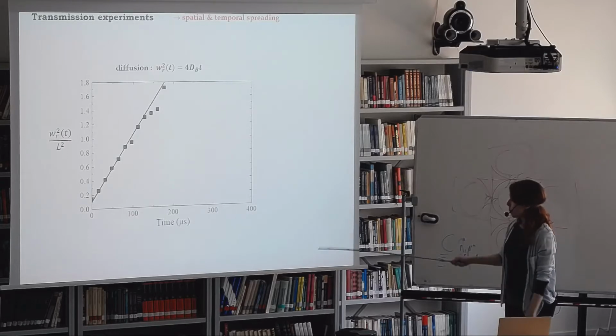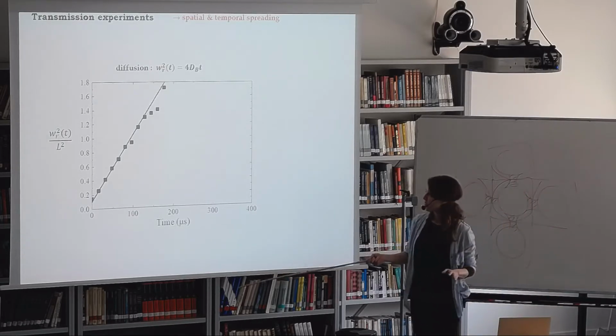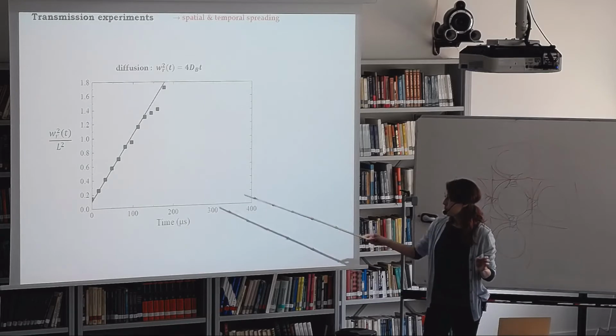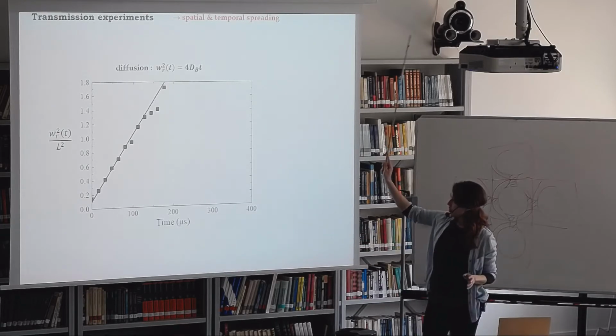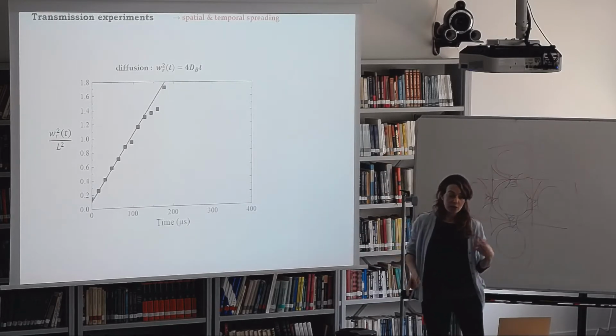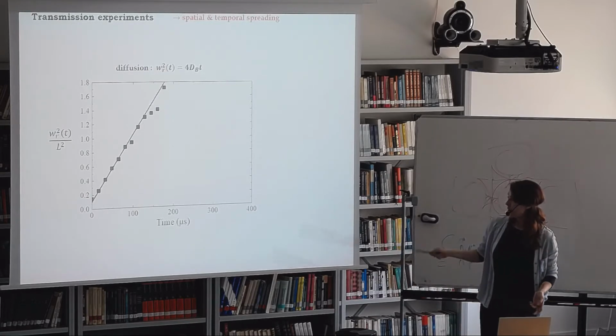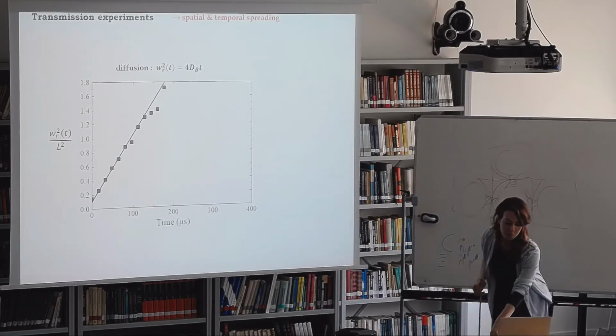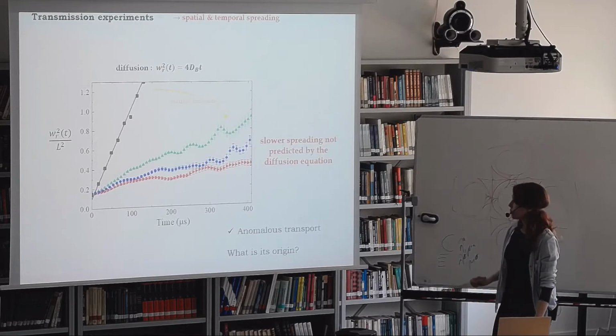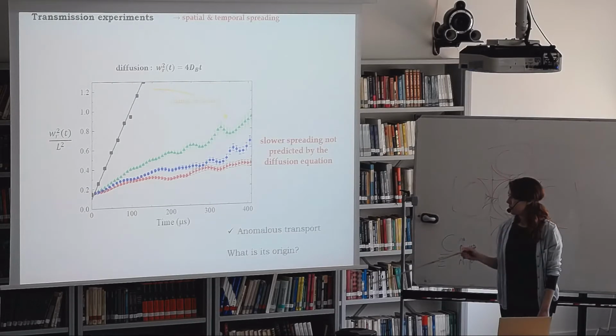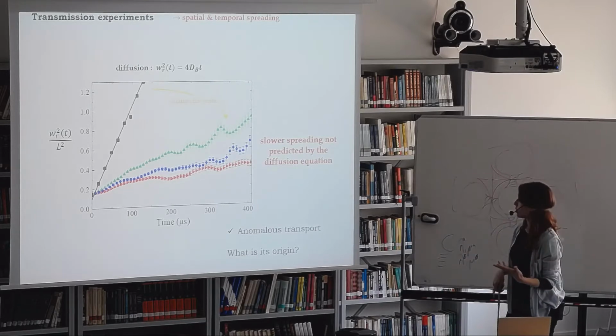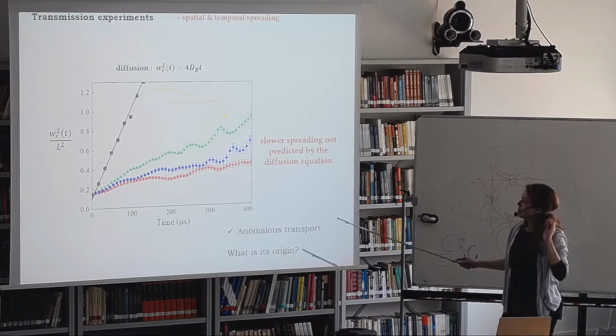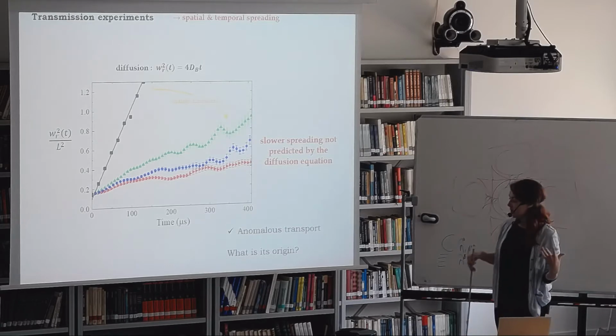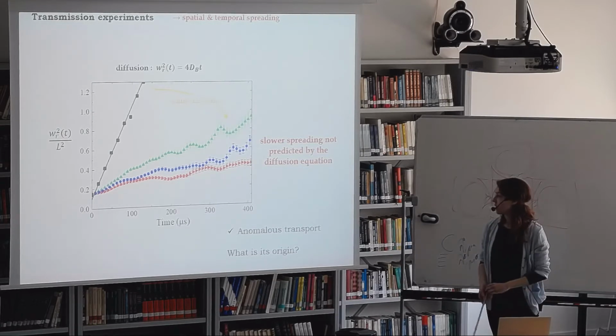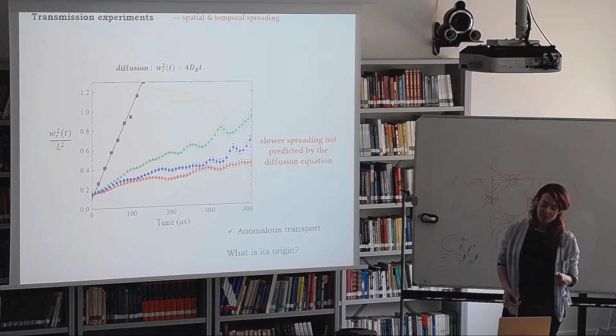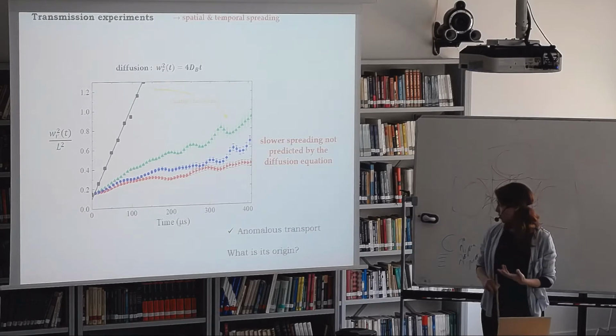Here we see the width squared, normalized by the sample thickness, as a function of time. As predicted by diffusion, it increases linearly, and we can even use this to measure the diffusion coefficient just by fitting it with a linear fit. However, at other frequencies, the data does not fit the diffusion approximation. So we see even the way that the waves are spreading is slower than has been predicted by the diffusion equation. So this is a more unambiguous measurement of anomalous transport.